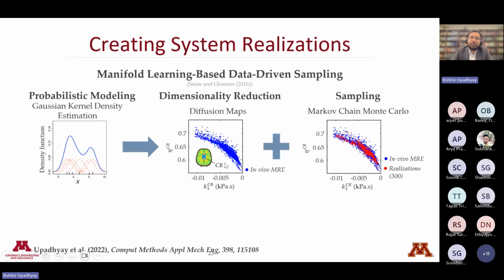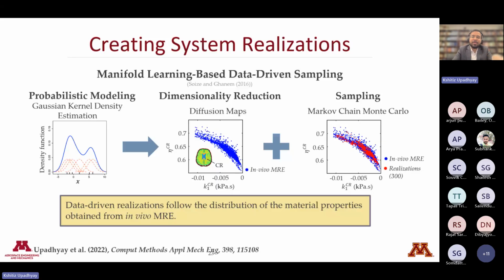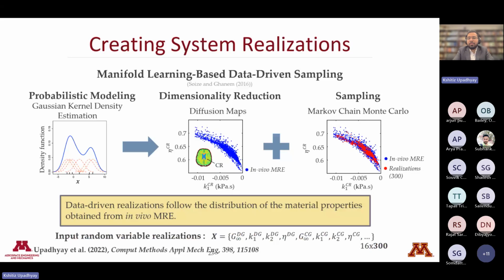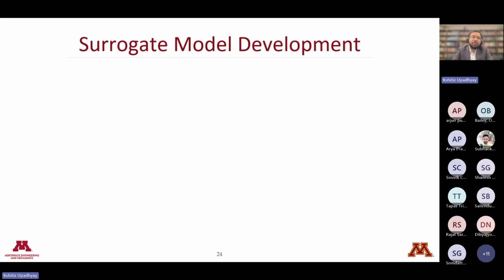When we use this method, we got these new realizations. These realizations lie right on top of the in vivo MRE data. That means the approach was able to do the probabilistic modeling of the input data. So this method helped us create multiple realizations that follow the distribution of mechanical properties from in vivo MRE. Using this method, we created 300 realizations of the system. You can think of them as 300 computational models. Each model has a different set of 16 material parameters, obtained using this manifold learning-based method. Once we have those 300 sets of models, the next step was to train a surrogate model. As I said, surrogate modeling is difficult here because the input and output dimensionality are very high.